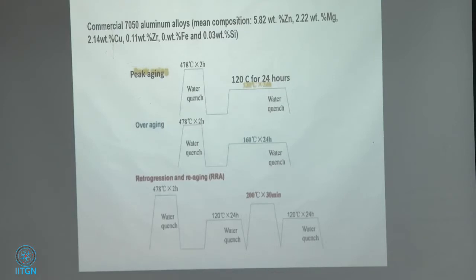Now in retrogression and re-aging, we do solution heat treatment, and then we do this peak age treatment, okay? And then we go for this treatment, 200 degrees C for 30 minutes, and then we do another heat treatment, 120 degrees Celsius for 24 hours. So this is your annealing step in between. So it's not 478, it's 200 degrees C for 30 minutes. That's your intermediate step, which is going to give you that overaged condition. And then you go back to the peak aged again. So dual treatment. Of course he played with these numbers many times to get it right.